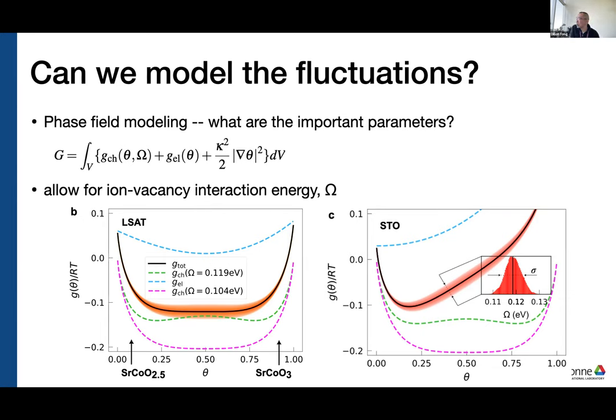relatively important parameters? So with Ganesh, we worked on this free energy equation that's made of three components. One is a chemical component, one is an elastic component, and the third component is a gradient energy. So that's like the interface energy between the Brownmillerite and the perovskite. So they looked at